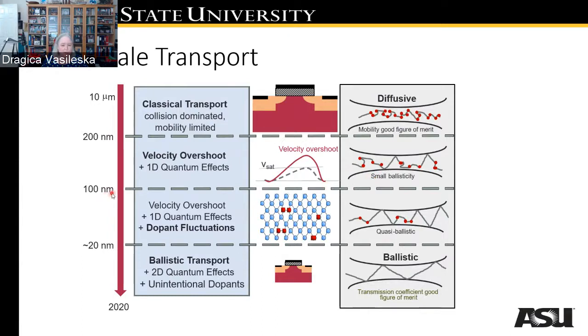Below 100 nanometers, in addition to the velocity overshoot effect and 1D quantum effects, one also has to worry about dopant fluctuations. In other words, because of the stochastic nature of the process of ion implantation, we can have different number and different distribution of the impurity atoms in the active region of the device, which in turn can lead to fluctuation in the device, for example, threshold voltage, from device to device fabricated on the same chip.